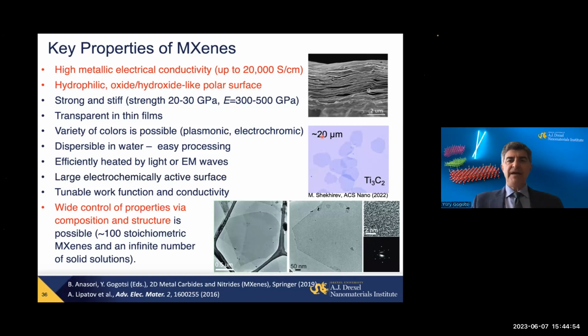But it all makes sense only if the properties of these materials are better than other materials. And actually they are. I already gave you an example of conductivity. We get even over 20,000 Siemens per centimeter. Reduced graphene oxide typically has 2,000 to 4,000. So the material which is used in such multilayer films for various conductive applications is 10 times less conductive than MXene. And you don't need to reduce it. You just process and dry the film. You don't need to heat it up. You don't need special treatment, like with graphene oxide, to go to a conducting structure.